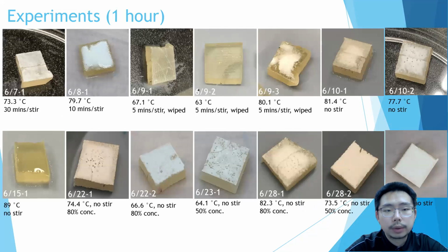Here are some of the pictures of the specimens from my experiments. I have tried different temperature, stirring intervals, solution concentrations, and pretreating methods. So far, I found that around 70 degrees Celsius, 50% concentrations and pretreated with ultrasonic bath works the best. As you can see on the very last two pictures, zinc oxide nanostructure were very evenly spread on the top of the 3D printed parts.